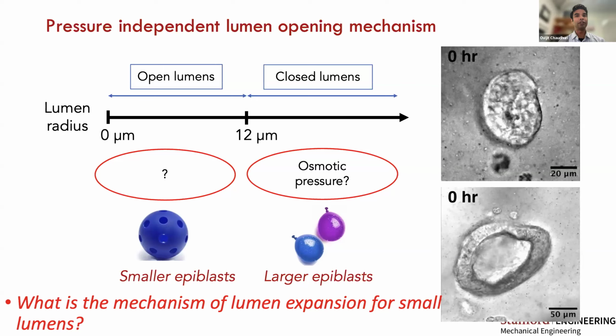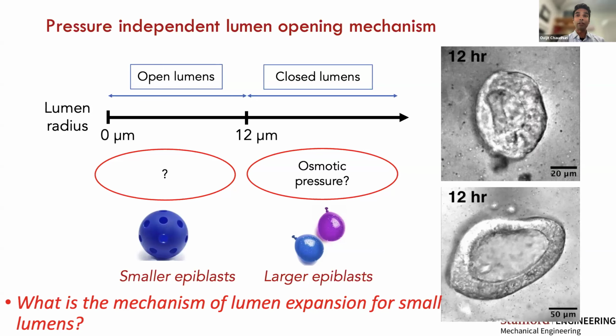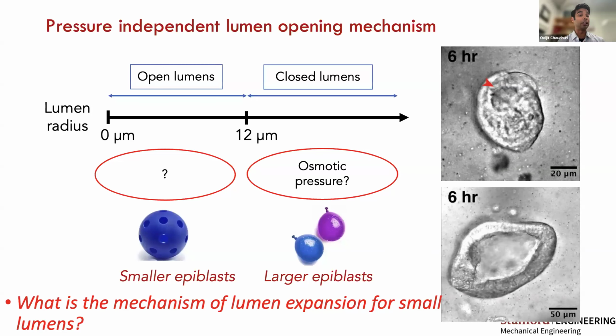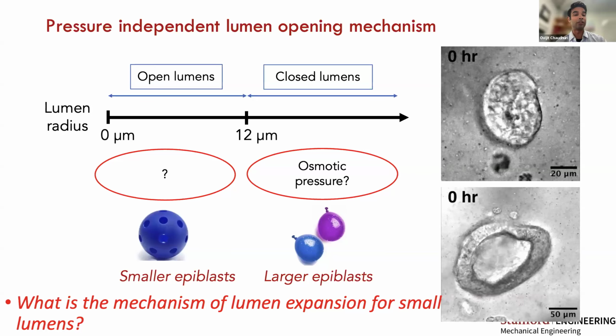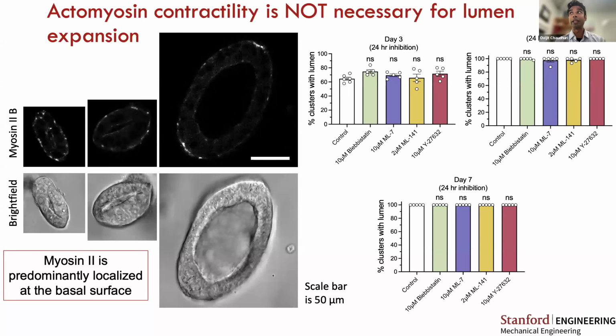So this lumen expansion mechanism must be associated with some kind of force generating mechanism. That led us to start to look at different force generating mechanisms and whether they could be associated with luminogenesis. We first started out by looking at actomyosin contractility. We inhibited actomyosin contractility using various inhibitors and found that it had no effect on luminogenesis, as you can see from these quantifications here. So actomyosin contractility is not driving lumen expansion in our model.